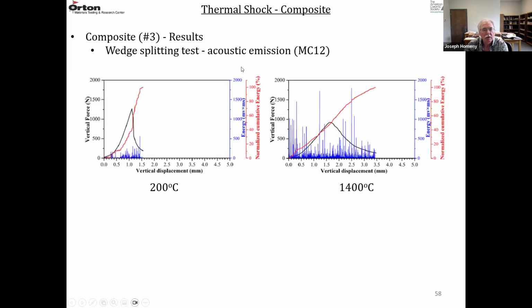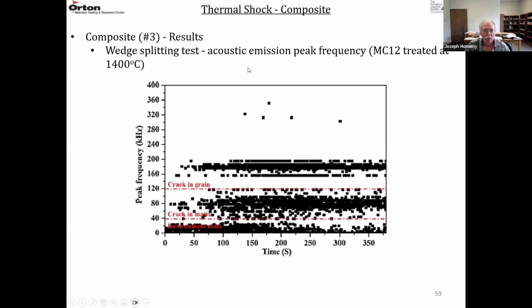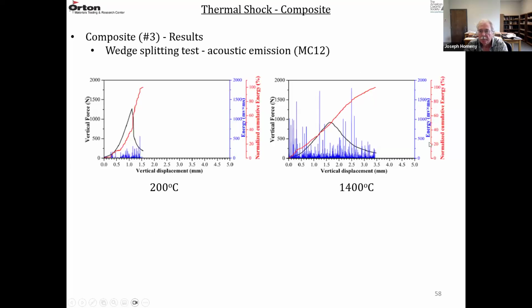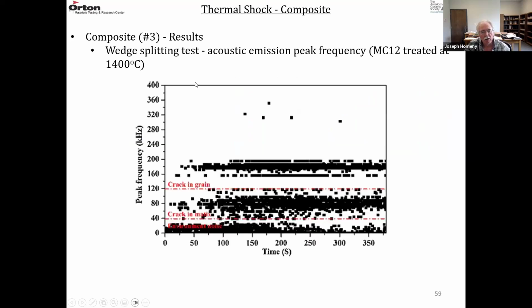And then they did the same thing for MC12. Again, it's force versus displacement. The black is the wedge splitting. You can see that the 1400 degrees C is more ductile. The 200 degrees C is more brittle. You can see the acoustic events. And you can also see that all the way down this crack propagation after the peak, you still have all these events taking place, absorbing energy. So this height or frequency of these acoustic emissions, the height, you can correlate it to a fracture process.